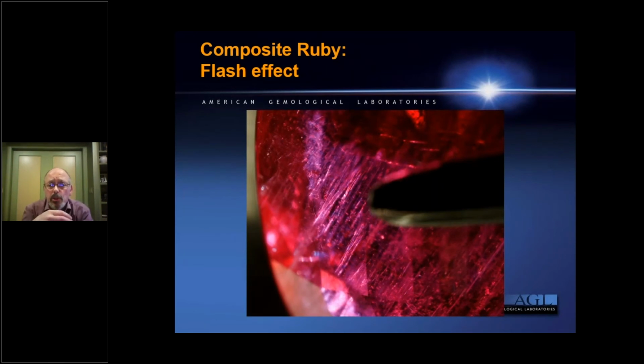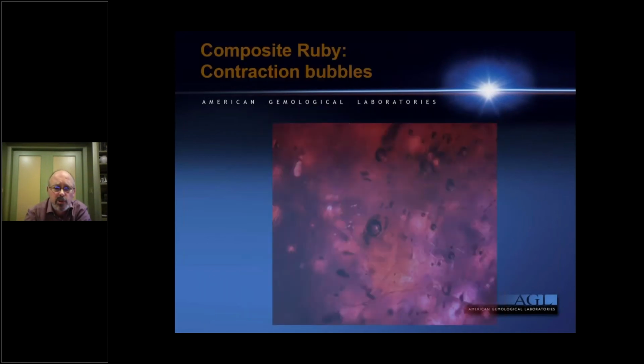Some of the things that you can look for: a bluish flash effect. These give a kind of hazy appearance to the stones. You can see this readily with a loupe. You don't need a microscope for this. Even by eye, if you've seen enough of these, you can start to visually recognize there's something a little bit different in the color and the transparency of these stones. But these are all fissures, so you get this blue flash effect throughout the stone.